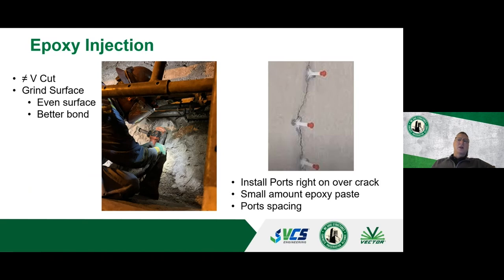Because you're installing these injection ports, that's on the right-hand side. Those are the injection ports, and you add those ports right over the top of your crack. And so that's why I say V-cutting is not always necessary, because you're putting those ports on top of it. So if you make the diameter of that crack larger than it is, then you can have some struggles. But you want a nice flat surface to be able to get those ports installed.